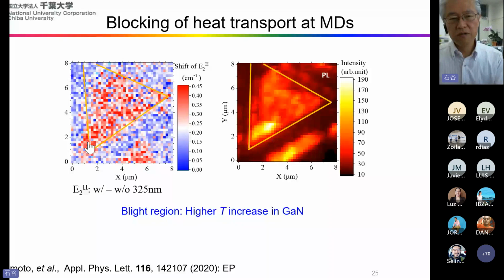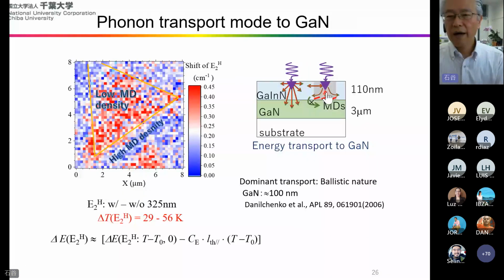So this structure says that at the defective region, phonons cannot be transported to the underlayer. But in the high crystal quality region, phonon transport and thermal conductance are high. So the crystal quality is very important for the extraction of thermal energy. And we have successfully monitored this phonon transport across the heterointerface. This is published in Applied Physics Letters, and this was designated as an editor's pick.